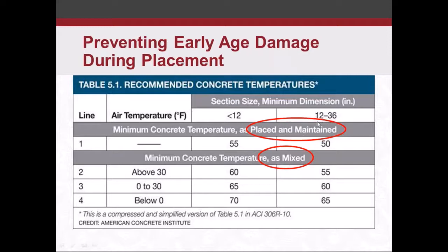This dimension over here, 12 to 36 inches. So these are larger dimensions. But the minimum concrete temperature placed and maintained for these smaller, thinner sections, we're going to keep that at 55 degrees. For the larger ones, we can go down to 50 because we're kind of using the heat of hydration from that larger concrete placement. Although not considered mass concrete, it's just the mass of the concrete.